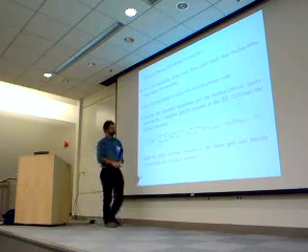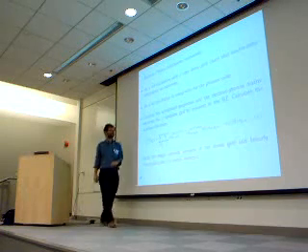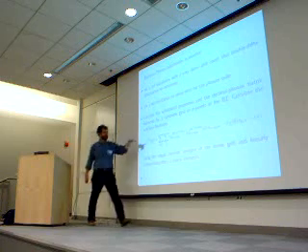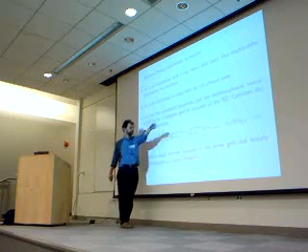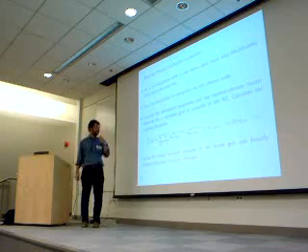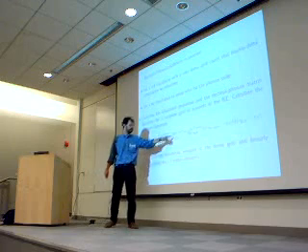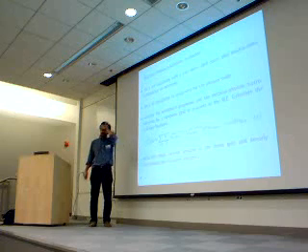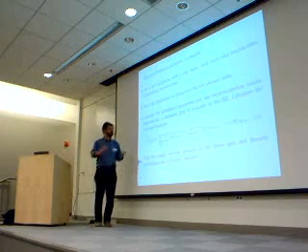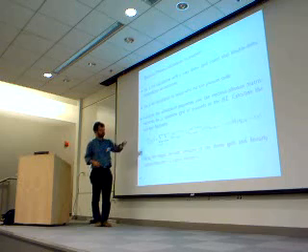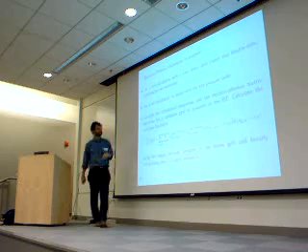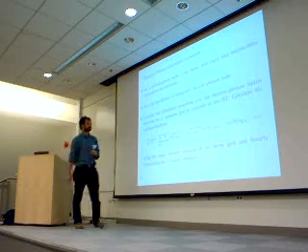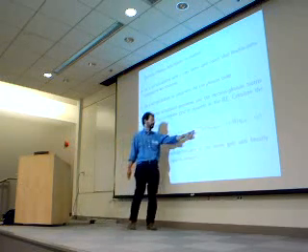So S and alpha describe an elementary displacement in the unit cell that then is repeated, getting an e to the plus iqR phase when you move in neighboring cells. So S alpha is an elementary displacement, not an eigenmode, and you need to calculate a square, and in this square you need to include not only the diagonal elements, but also all the off-diagonal elements.